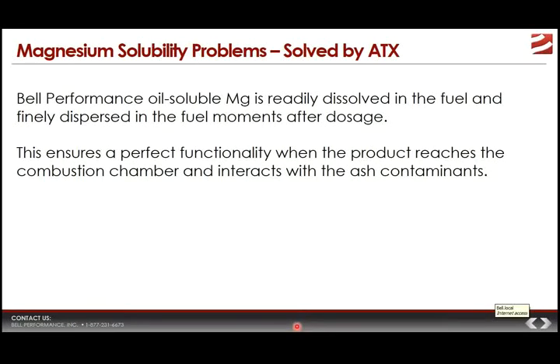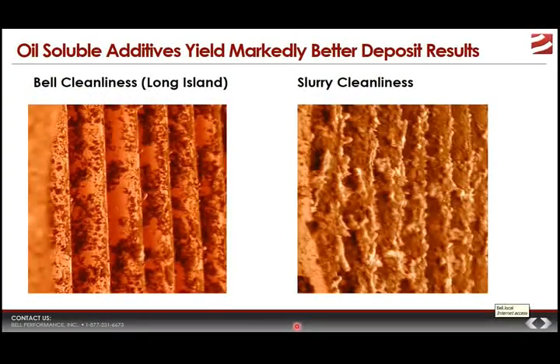Contrast that with the oil-soluble magnesium in ATX. Since it is oil-soluble, that means it's dissolved in the petroleum. When you add that to the fuel oil, it disperses and dissolves evenly. That means you're not going to have any settling issues, and you can be pretty sure that you're going to have a homogeneous and even distribution, and that's an important consideration to have.